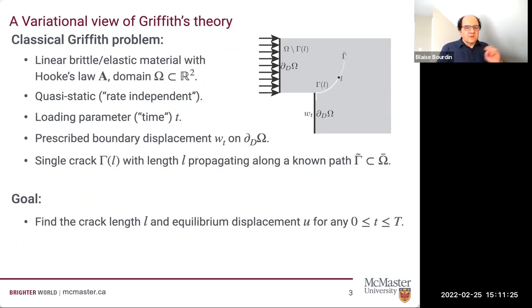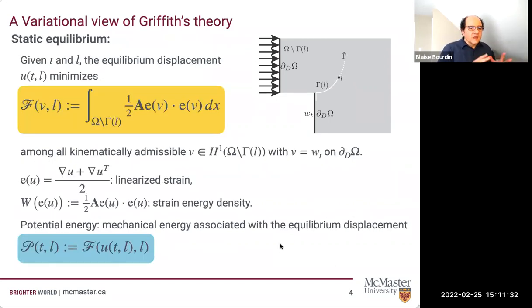So we're going to do that step by step. The first step is to not worry about the crack, but just look at the equilibrium displacement. So what we're going to do is fix the displacement. We're going to do the prescribed displacement. We're going to fix the crack length L. And okay, classical theory of continuum mechanics tells you that given t, so the loading, and L, the crack length, and if you know L, again, you know gamma of L at this stage, the equilibrium displacement minimizes the mechanical energy. So that's the 1/2 of A E of V, where E of V is called a strain energy density associated to a displacement V. The E is the symmetrized gradient, that's also called a linearized strain.